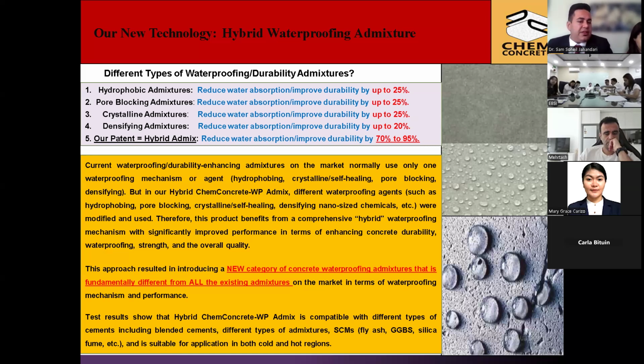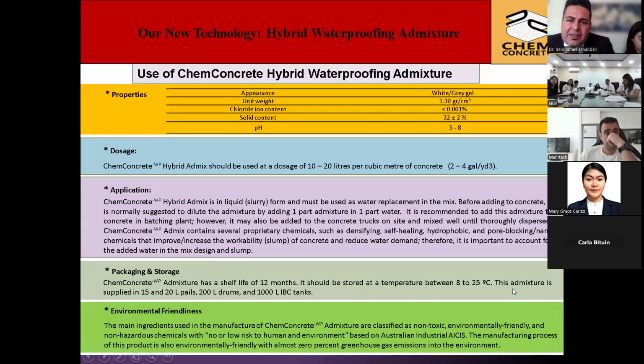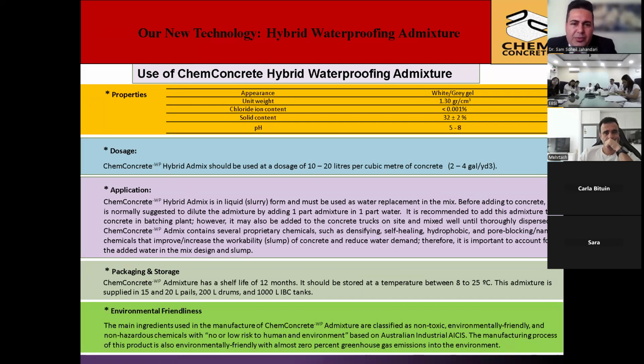And the good thing is that the test results show that this product is compatible with different types of cements, including blended cements, different types of admixture, supplementary cementitious materials like fly ash and GGBS or slag, silica fume, and also it's suitable for application in both cold and warm regions. It's usually in a white to grayish color, and it's normally suggested to be used at a dosage of 10 to 20 liters per cubic meter of concrete or 2 to 4 gallons per cubic yard. But sometimes we've noticed that 5 liters per cubic meter is also used. And we supply this admixture in 15 and 20 liter pails, 200 liter drums, and 1000 liter IBC tanks.